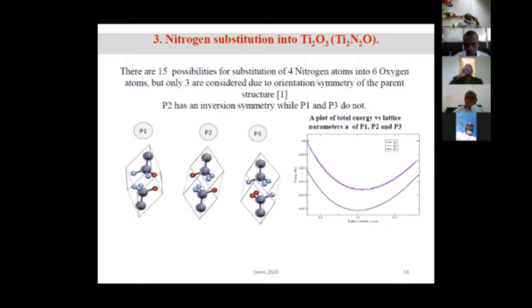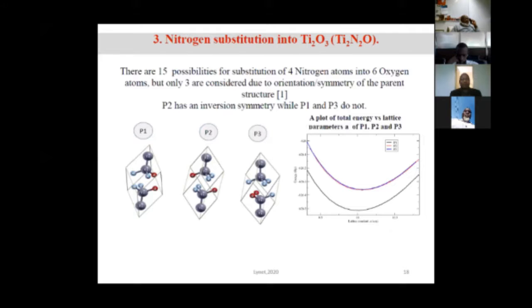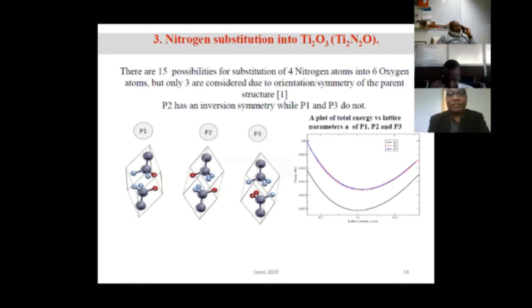Then we went ahead and substituted nitrogen into the Ti2O3 so that we get Ti2N2O, the oxynitride, in the ratio of the elements in the formula. We had an option of 15 possibilities, which you can find when you work out the permutation, the number of ways in which 4 nitrogens can be substituted into 6 oxygens. That is 6 factorial over 4 factorial times 2 factorial, which gives 15. But we didn't consider all 15 possibilities because of the nature of the parent structure. We simply considered 3.